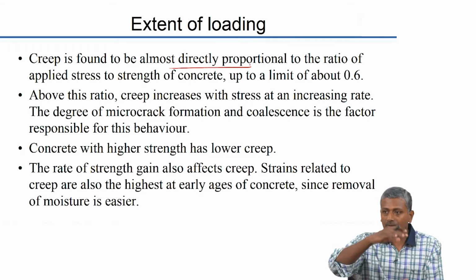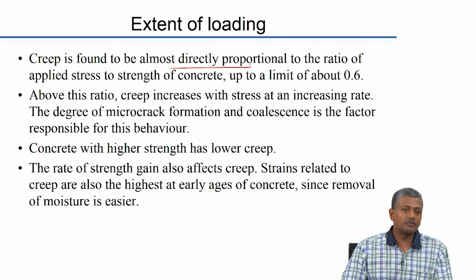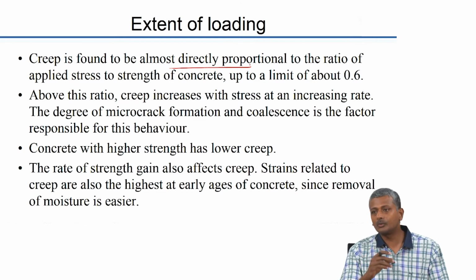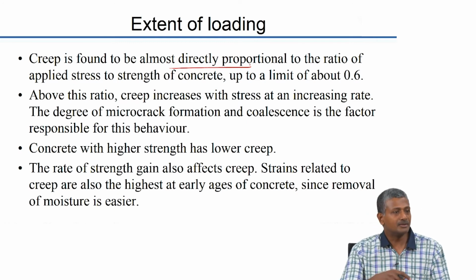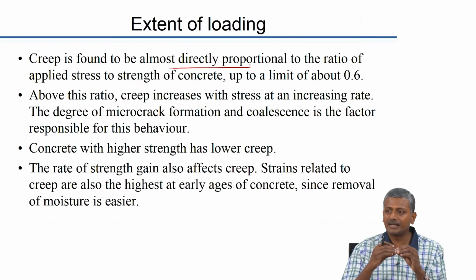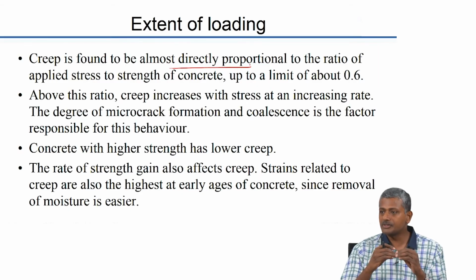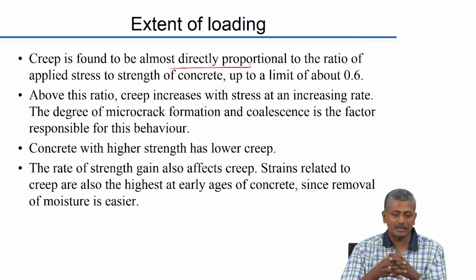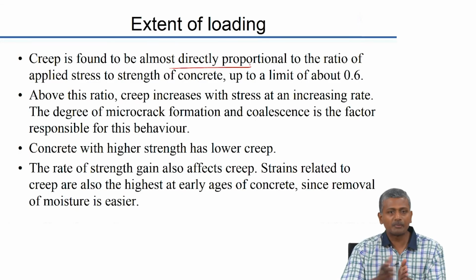When you load your concrete in compression, up to 30% or 40% you have only minor cracks in the ITZ. When you increase this load to about 50-60%, your ITZ cracks only start getting bigger and bigger. So, since your cracking is still located only in the ITZ, your creep does not increase drastically. So, it is almost directly proportional to the extent of applied stress to strength ratio.